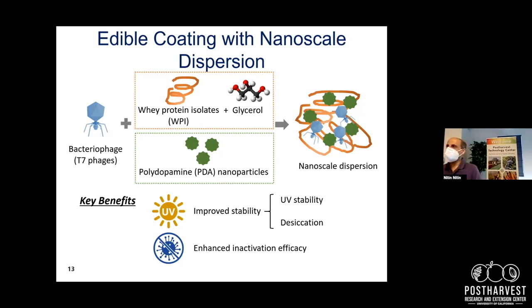Now, one of the challenges that came up is that, like many other agents, these viruses are very susceptible to light as well as desiccation. So if you put it on a produce and it goes through a desiccation cycle, you lose significant activity of this agent. So our objective was how we can use the concept of edible coating in this case to maintain the activity of the biocontrol agent. So in this case, the edible coating is not only providing a protective barrier against the loss of water or respiration, but also actually protecting the active biocontrol agent that you have in the formulation.